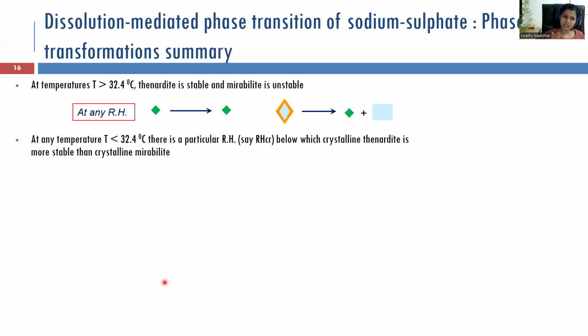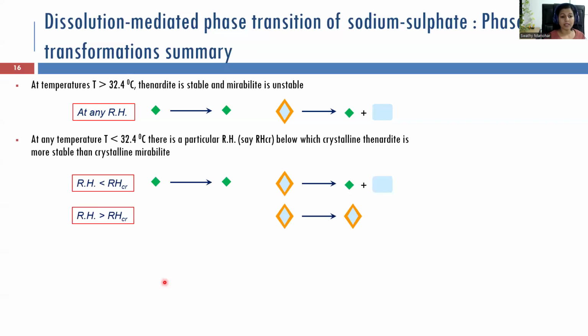When the temperature is reducing to less than 32.4 degrees Celsius, if the relative humidity is high enough, then it is mirabilite. But if the relative humidity is getting reduced to something less than a relative humidity critical value, then thenardite is going to be stable. So if the relative humidity is smaller, then again mirabilite will convert to thenardite. Thenardite will remain thenardite at lower temperatures. But at lower temperatures, if the relative humidity is higher, then mirabilite is the stable phase.